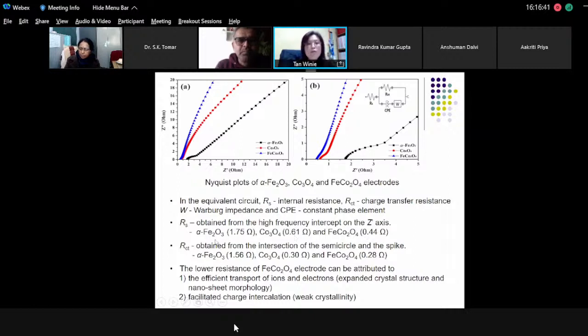The same thing for the charge transfer resistance, where the iron cobaltite shows the lowest charge transfer resistance. You see for both RS and RCT, the low resistance of the iron cobaltite electrode can be attributed to the efficient transport of ions and electrons as a result of the expanded crystal structure and the nanosheet morphology of iron cobaltite. Okay, and also the weak